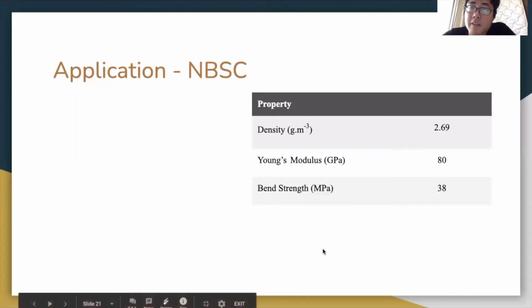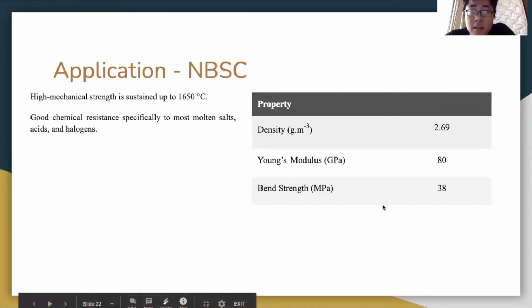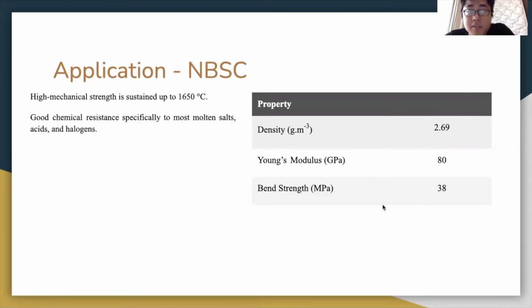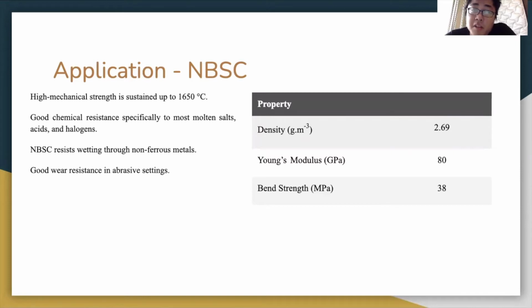Here is a table of NBSC properties: density, Young's modulus, and bend strength. As you can see, it has a high mechanical strength, which can be sustained up to 1650 degrees Celsius, and it has a great chemical resistance against molten salt, acid, and halogens. NBSC also resists wetting by non-ferrous metals, and just like SSC, it has a great wear resistance. And NBSC can also act as a semiconductor at high temperature.